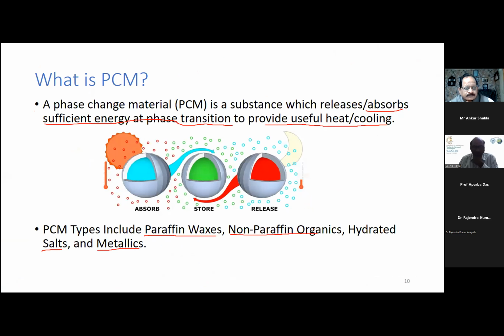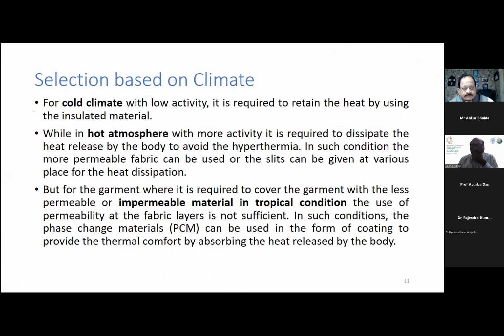So in this, the type of PCM selected is based on the climate. For cold climate with low activity, it is required to retain the heat by using insulated material. And for a hot atmosphere with more activity, it is required to dissipate the heat very fast, like sportswear, the ones which are purely made from 100% polyester fabrics with high wicking capacity to avoid hyperthermia.